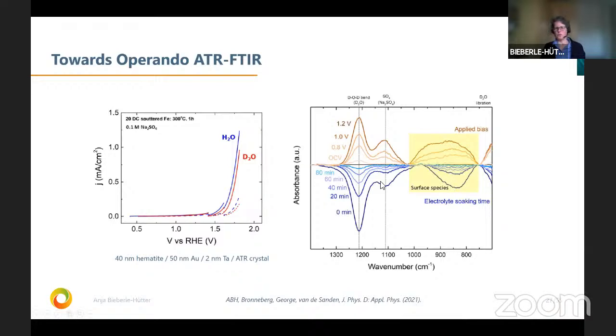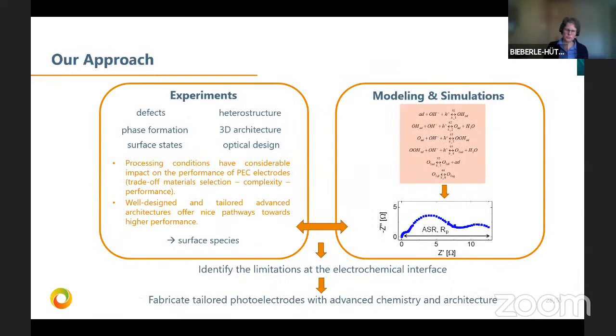What we learned from this is that we have to wait about an hour, 1.5 hours, to have a stable structure. And then we could apply bias, in another set of measurements, and measure the impedance spectra and the FTIR spectra. And in this region where we expect the surface species, we really do see a change, a broadening. So what we have to do further is fit this data and do this under more different conditions, to really be able to say this is due to this or that surface species. But this is actually ongoing research.